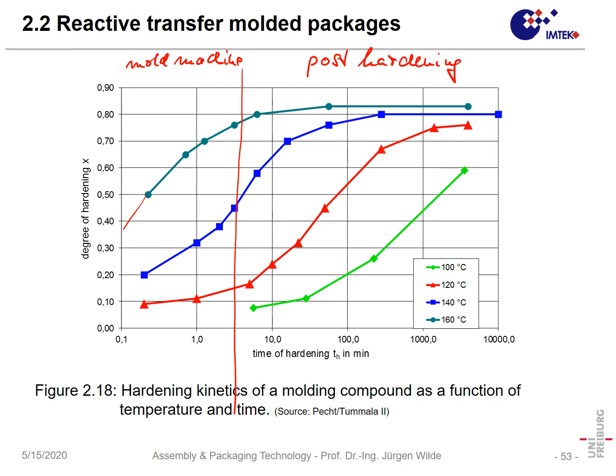So let's think about why not harden in the machine for 4 hours. That's straightforward. Then we would only be able to do one molding shot in the machine every 4 hours. And the molding machine is much more expensive than just a simple oven, which just has a temperature of 180 degrees centigrade. So it's much more efficient to mold in a short process and then to do this post-hardening.